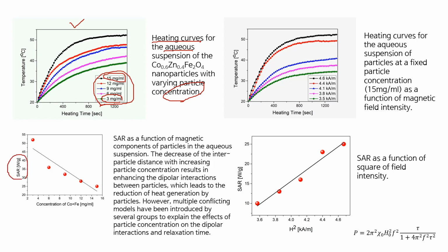So we plotted SAR as a function of the concentration of nanoparticles. You can see here, as the concentration of nanoparticles increases, the SAR is decreasing. Okay. So this figure shows SAR as a function of magnetic components of particles in the aqueous suspension. The decrease of the interparticle distance with increasing particle concentration results in enhancing the dipolar interactions between particles, which leads to the reduction of heat generation by particles. So SAR is decreasing as the concentration of nanoparticles increases.